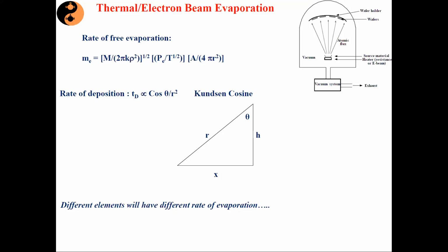Another limitation, particularly for thermal evaporation: you could simply say we can just heat. But remember, there are different elements whose melting temperature is way beyond the heating temperature which can be reached using these normal heaters, right? So even before your target material starts evaporating, your heating element itself will start evaporating. And if your heating element starts evaporating, it is different from your target material, and hence those heating elements will give rise to contamination in your thin film. Therefore, thermal evaporation cannot be used for those materials whose evaporation or melting temperature is much higher.